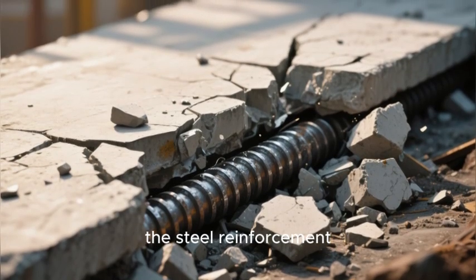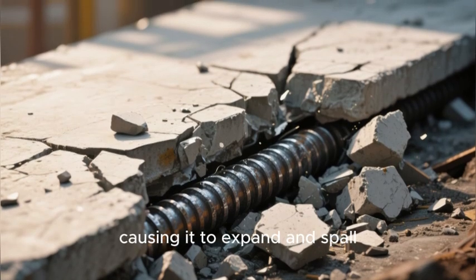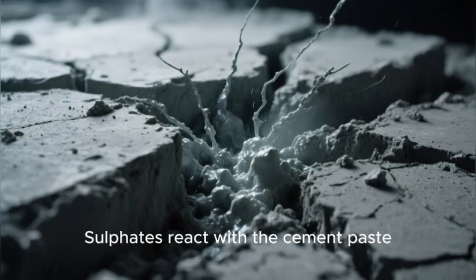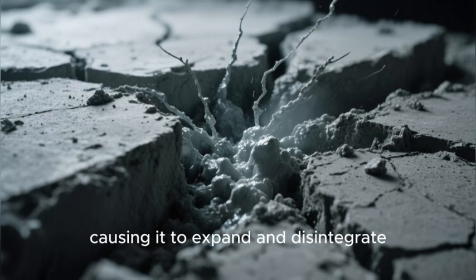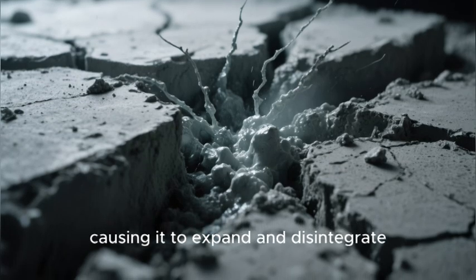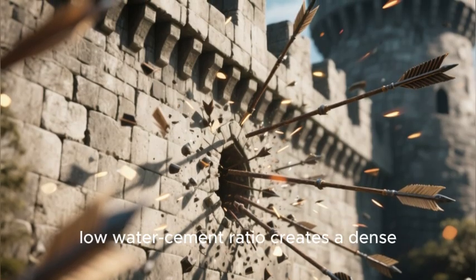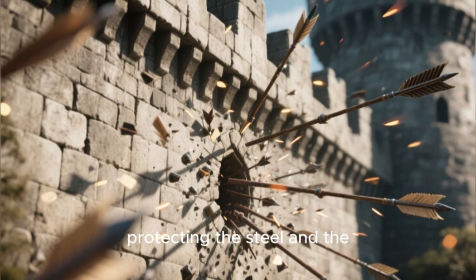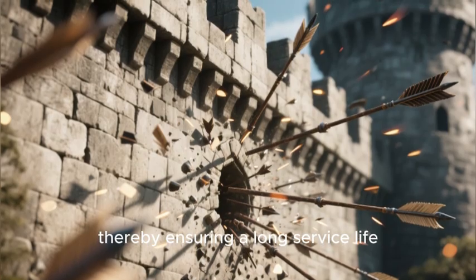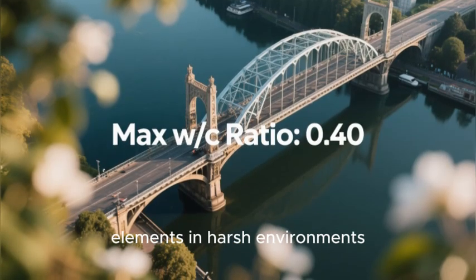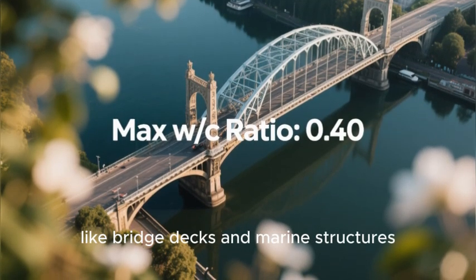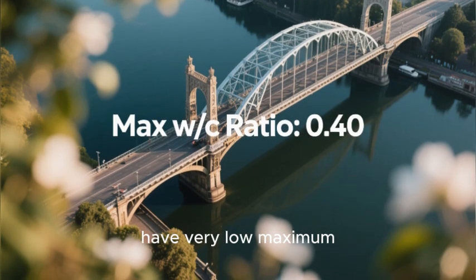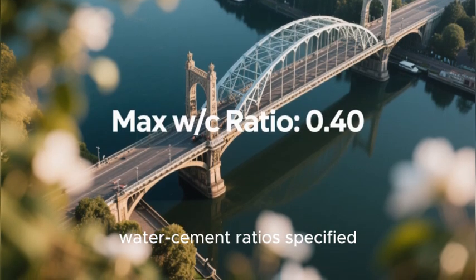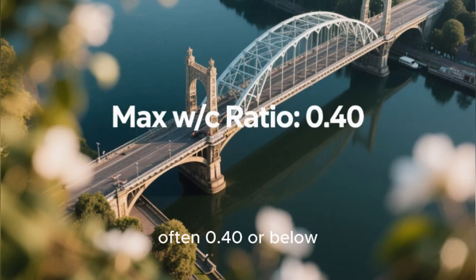chlorides corrode the steel reinforcement, causing it to expand and spall the concrete cover. Sulfates react with the cement paste, causing it to expand and disintegrate. A low water-cement ratio creates a dense, impermeable concrete that acts as a fortress, protecting the steel and the paste from these attacks, thereby ensuring a long service life. This is why key structural elements in harsh environments, like bridge decks and marine structures, have very low maximum water-cement ratios specified, often 0.4 or below.